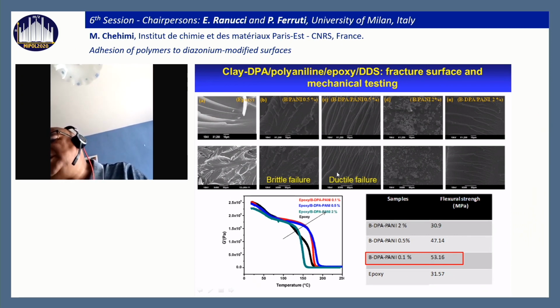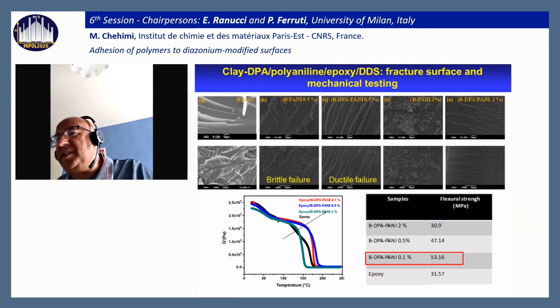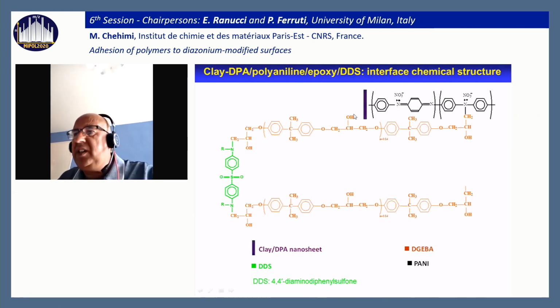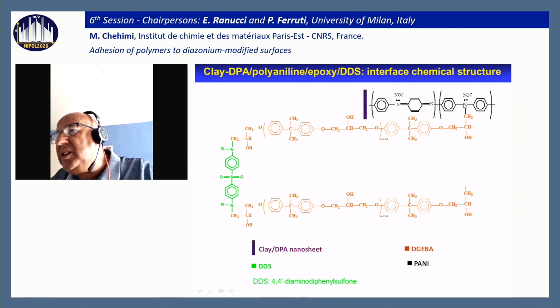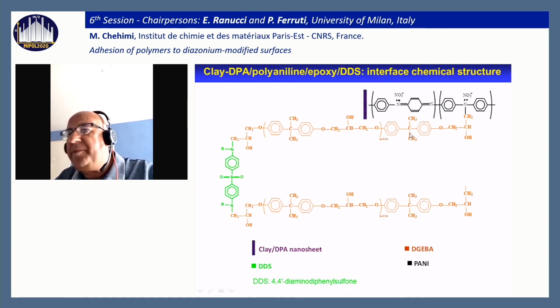Here we have a brittle failure, almost the same as if epoxy was not filled with the filler. And here we have a ductile failure, which is a sign of a very strong adhesion between the nanofiller and the epoxy. If we look at the interface here, we have the intercalation of the clay with the diazonium, the fabrication of the polyaniline. The polyaniline can also react with epoxy. We have the crosslinker of the epoxy resin here, and this is a schematic view. This is what we propose as a mechanism to make a cross-linked epoxy using the crosslinker and also the nanocomposite filler.